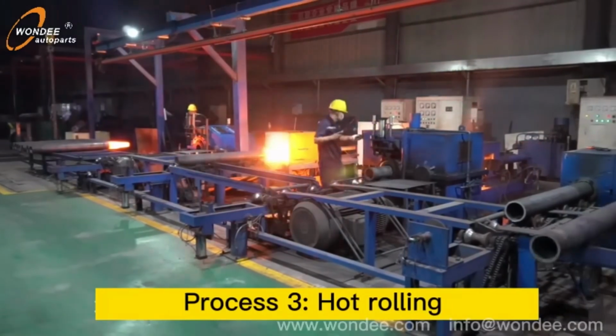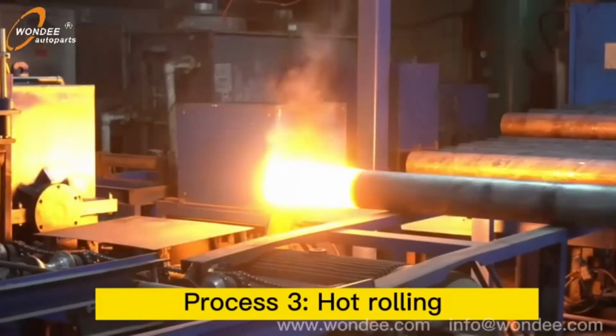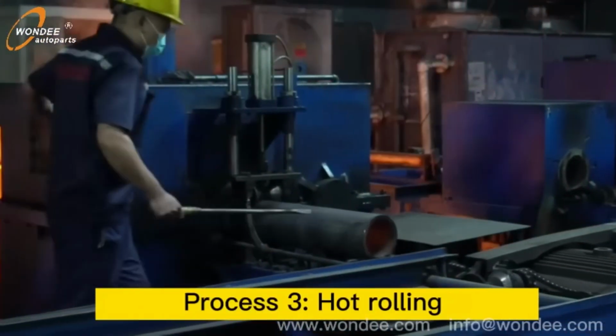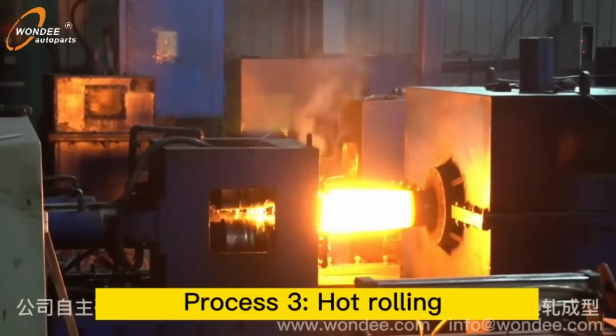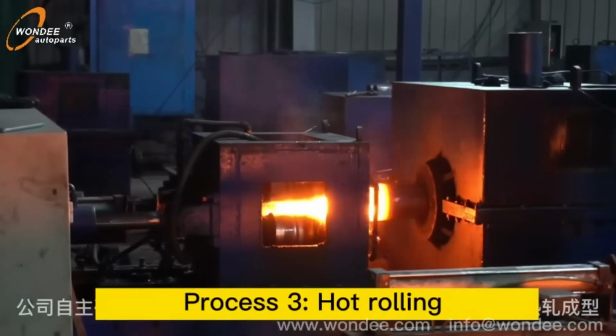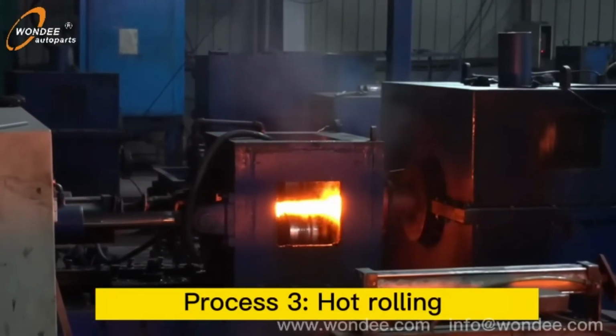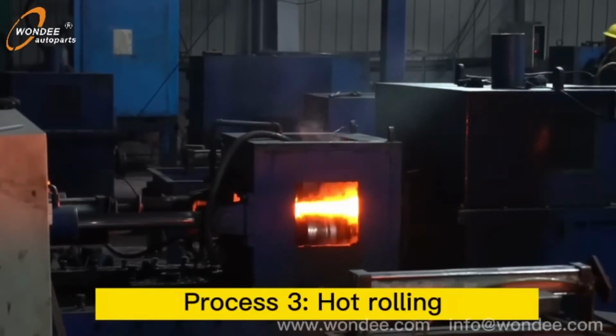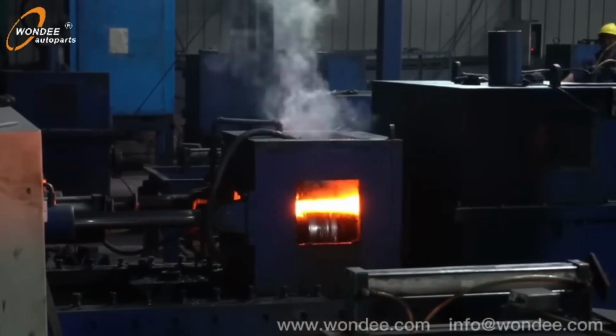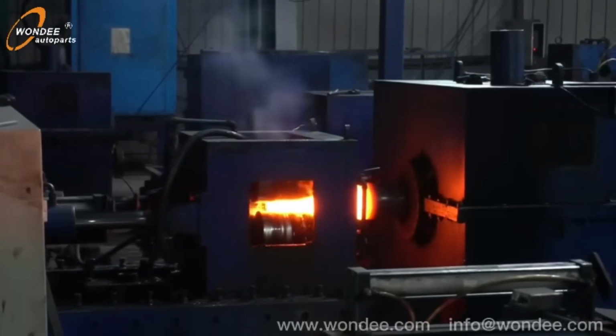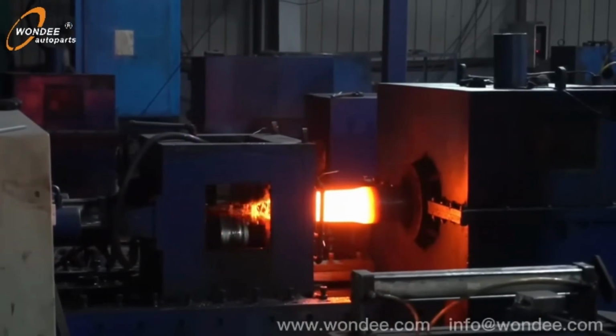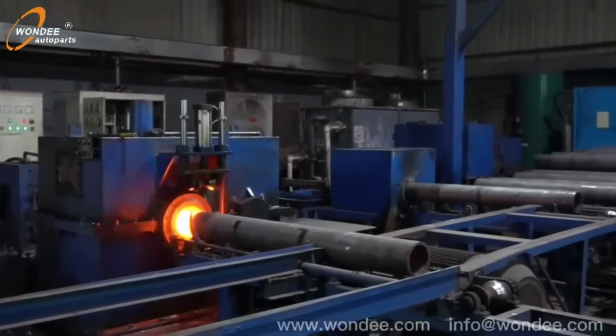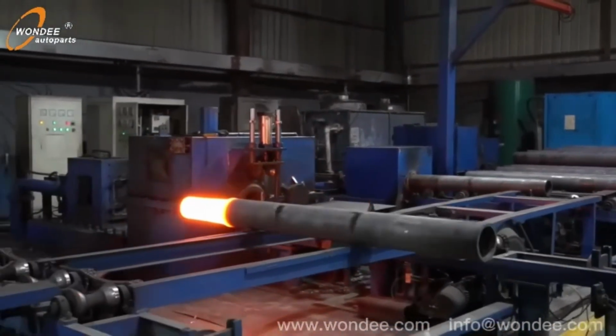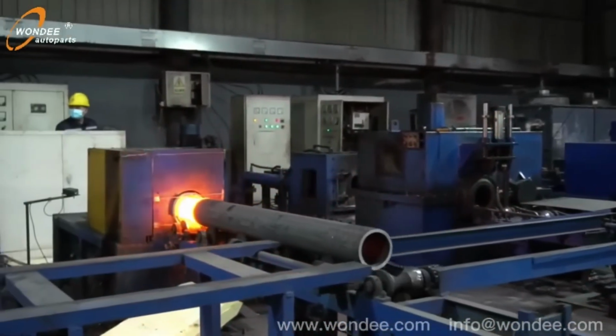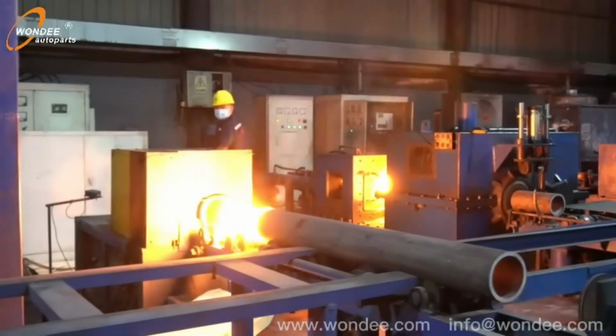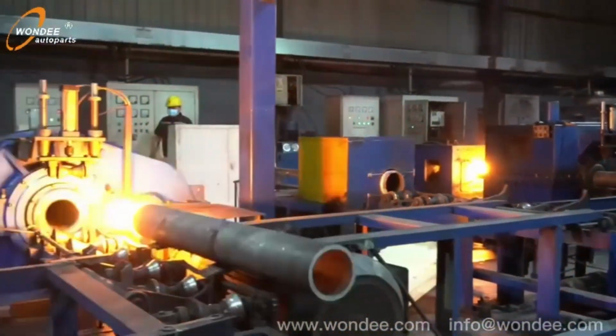Hot rolling in axle manufacturing shapes the axle tube ends into specific profiles required for spindles or axle necks. The process begins by heating the tube ends to high temperatures, typically between 1,100 degrees Celsius and 1,250 degrees Celsius, making the steel malleable. Once heated, hydraulic or mechanical rolling machines apply controlled pressure, gradually deforming the tube ends into the desired geometry. This operation not only shapes the axle ends, but also refines the steel's grain structure, enhancing mechanical properties like strength and toughness.